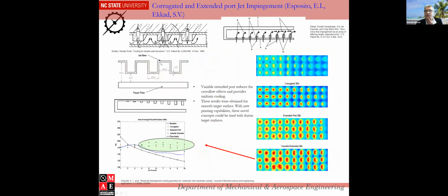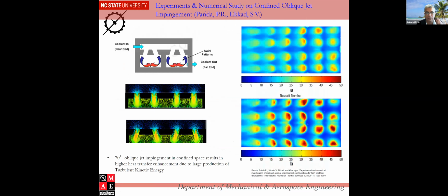One example of a very complex scheme we did many years back was to create an impingement channel like this, where the flow would come in and impinge here and then go into the side channels. It was patented. As you can see, US patent, we have a couple of patents. And we found that our heat transfer compared to a traditional impingement was significantly enhanced, especially downstream. So you can see the colors. As the color gets redder, the heat transfer is better. So that's one of the works we did in 2006, 2007.